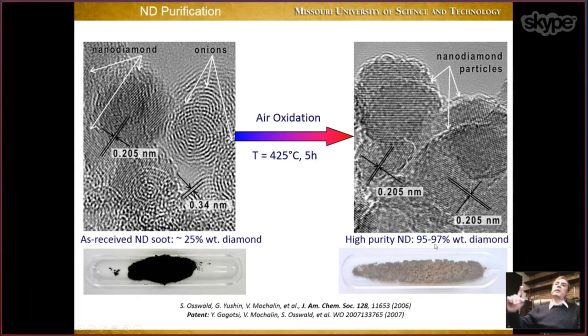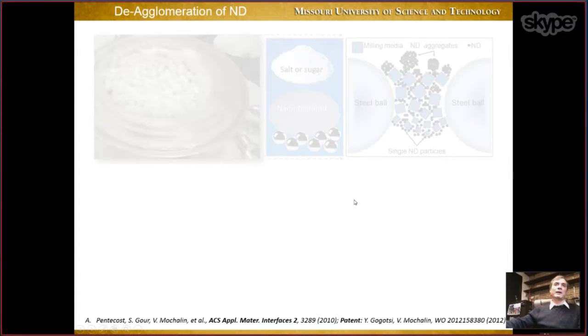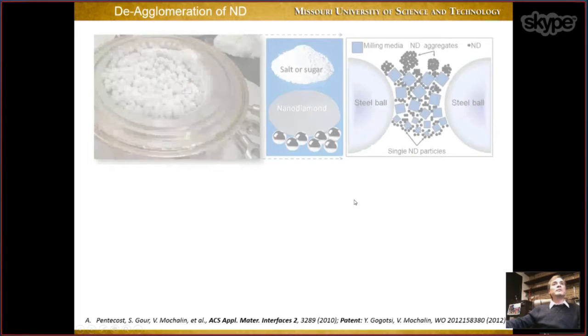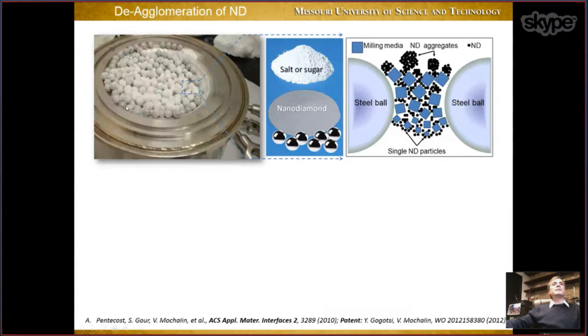And again, let me remind you that you can never expect 100% of diamond phase in nanodiamond simply because those dangling bonds on the surface have to be either terminated by heteroatoms or combine and form sp2 carbon, which is non-diamond carbon. Okay, so this is one of some of the highest contents of diamond you can expect in nanodiamond. Then we deagglomerate this material. To deagglomerate it, we simply mill it with such things as salt or sugar.